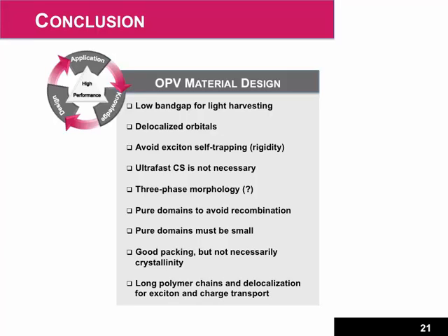You should have rigid polymers, because when they twist and change conformation in the excited state, that can really self-trap your excitons, and this can lead to certain problems. So always aim for something rigid with a small Stokes shift between absorption and emission, for example.